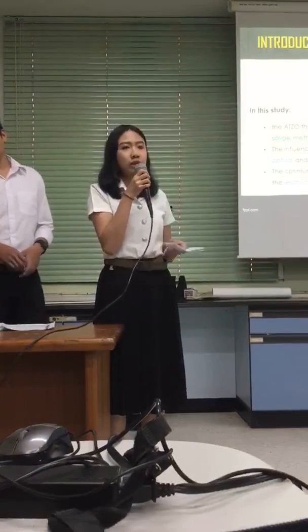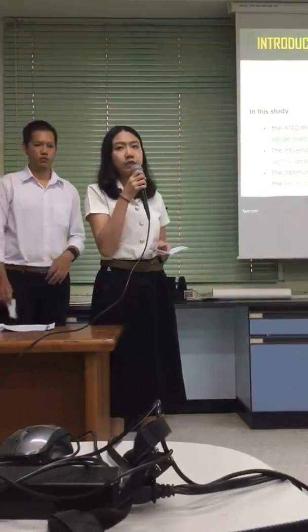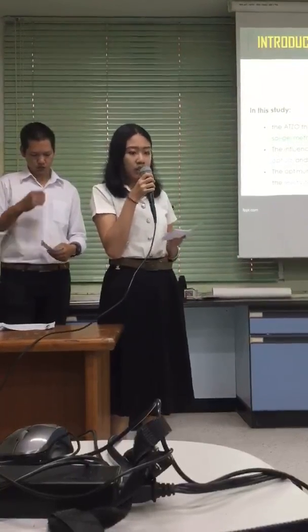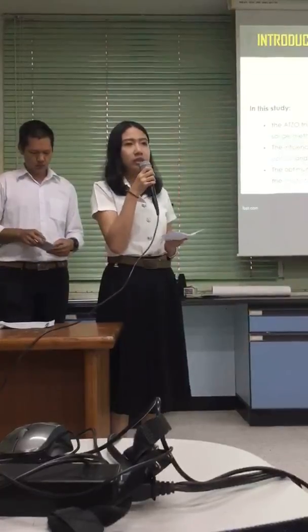In this study, ATZO is grown on glass substrate by sol-gel method. The influence of titanium concentration on structure, optical, and electrical properties. The optimum concentration of titanium was determined according to the resistivity and transmittance value of thin film.